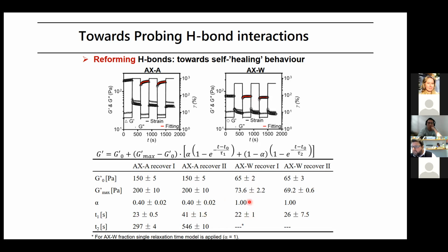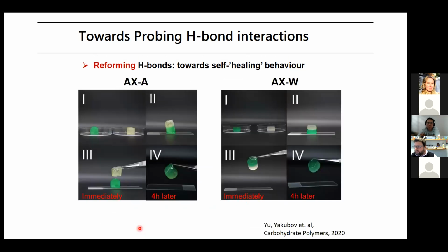But the alkaline fraction has a two-step relaxation. One is very similar to the water-soluble fraction, about 20 seconds, and another one is on the order of 10 minutes. So the junctions in the alkaline fraction relax in two ways. One is a fast relaxation, but then these consolidating properties are responsible for the longer relaxing fraction that relaxes on the scale of about 10 minutes.